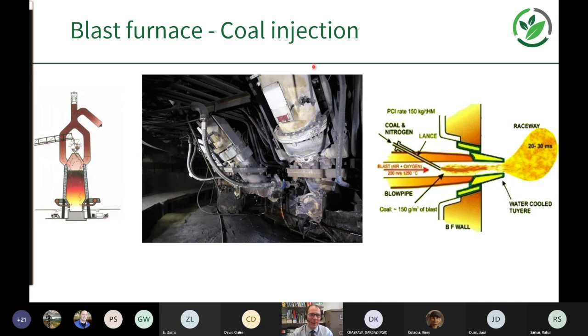So the picture in the centre shows the pipes which come down, which are the hot blast, the heated air that's directed into the bottom of the furnace. It's directed in through these nozzles, which are located around the bottom of the Bosh area of the furnace. That's called the bustle main, and that directs hot blast into the bottom of the furnace. And then you've got these braided metal flexes where coal is injected into the bottom of the furnace. On the right hand side, we've got this cross section of a coal lance, directing coal into the hot blast, and this tends to form a balloon-like void known as the raceway.